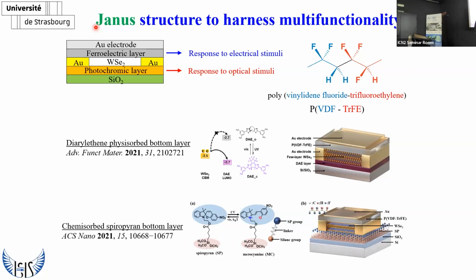In one case, we use a chemisorbed layer of spiropyran that has been functionalized with a silane unit that could chemisorb on silicon dioxide. And so the spiropyran group is exposed here on the top, therefore it's facing the surface of the tungsten diselenide. Then the rest is the same: the tungsten diselenide, the ferroelectric layer, and the gold contact. And here, that is the case I will explain more thoroughly, we have a diarylethene layer that is the same that we've been using so far.